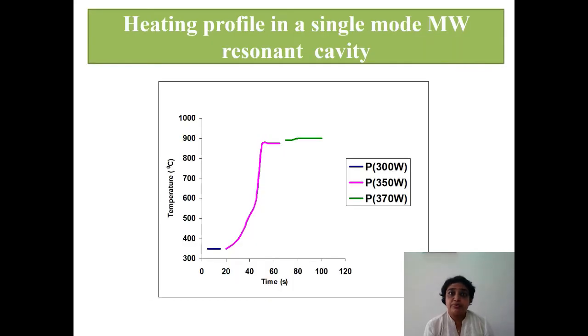So moving further, the heating profile in a single mode microwave resonant cavity. Just now I mentioned that in single mode, cavities are designed to enhance the electric field or magnetic field intensity at the workpiece location. Due to the very high field, the heating rate is very high. Again, here you can see some plots between temperature and time, and we can see that in a very short time, just a few seconds, 100 seconds, the temperature rises from room temperature to 900 degrees centigrade. Initially the power applied was 300, and this power was varied, because as the sample heats, its properties change, both electric and magnetic.